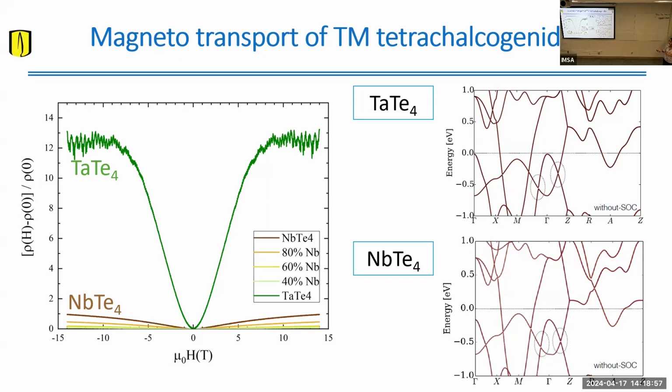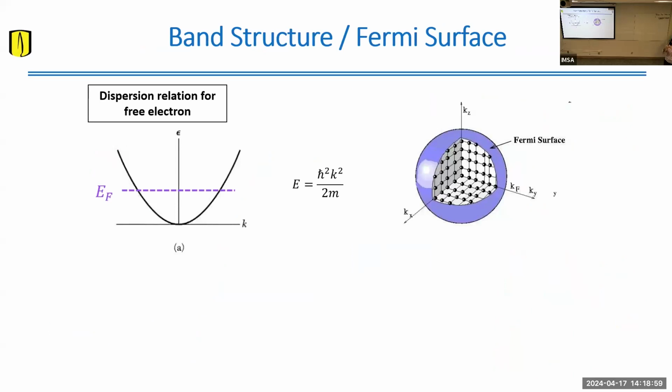They have checked. Right. So how can we reveal the electronic structure? One method is ARPES, which will give you access to surface states, but we wanted to go into a more thermodynamic way of determining the bulk electronic structure for this compound. And the best technique to do that is to measure quantum oscillations, or the Shubnikov-de Haas effect, which is tracking the oscillation that you have as you quantize electronic orbits in a magnetic field for the system.